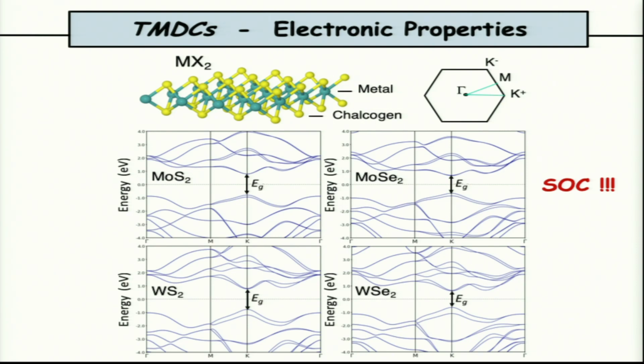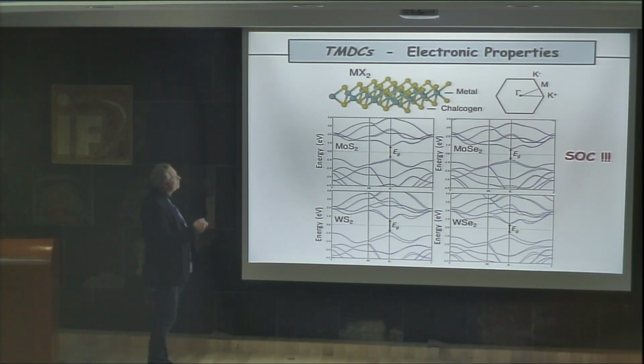Other examples are TMDs, and TMDs have already been introduced by Anna Laura yesterday in the nanoscience school. So they are mostly layered planes like this, which have a certain height in this case, where you have metal atoms, which is the M here, and a chalcogen, which can be, for example, sulfur or selenium. And in this case, you see that most of the structures are semiconducting, but what is interesting is that when the material is a bulk system, so you have a stacking of these planes, you have an indirect band gap. But when you come to a single plane, you see the band gap becomes direct. So this is extremely interesting, for example, for optoelectronic devices.